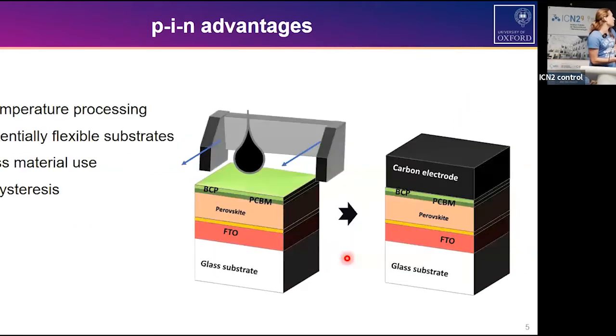So this is why I am going to use a PIN architecture. I started off using exactly the same configuration we use in our metal cells, and just simply blade coat carbon on top of a ready stack. So you have the entire stack finished, and then you apply the carbon, doing the exact same thing as when you put it in a metal evaporator, but you blade coat carbon on top. That was the first idea, so we can build on all the knowledge and experience we have with our existing stack.